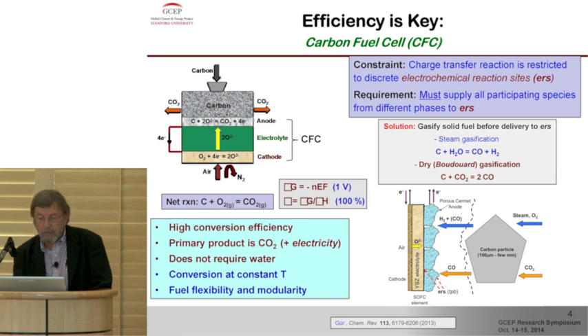So one of the techniques to overcome part of this problem is to gasify the solid fuel, using steam for steam gasification, where we react carbon with steam to form hydrogen and CO, which is a syngas, and then oxidize this hydrogen and CO, which through gas diffusion gets to the electrochemical reaction site at that interface and oxidizes. But we chose to use CO2 as a dry gasification method. CO2 is our anode reaction product. So what we do is, in a way, recycle that reaction product back to our system.